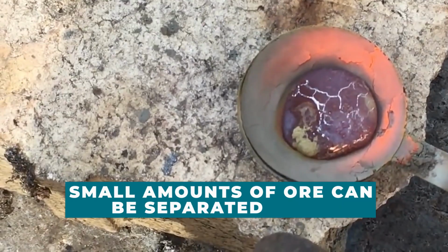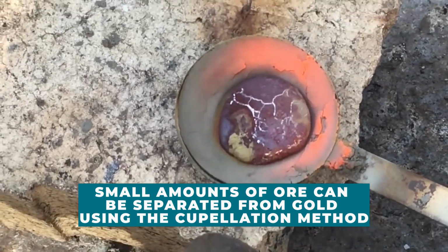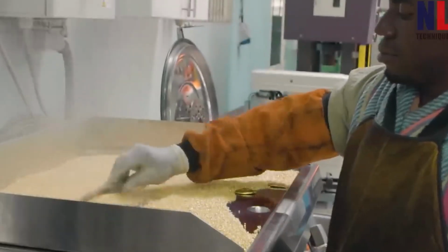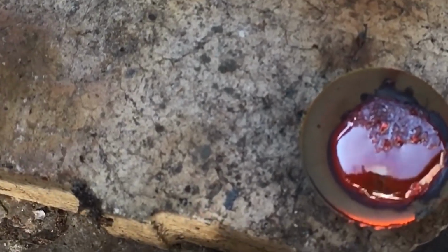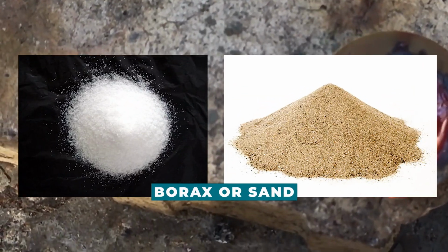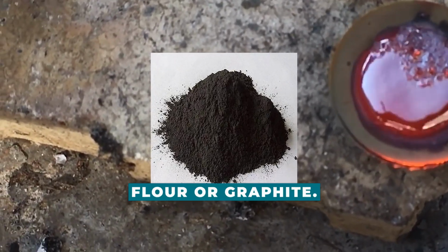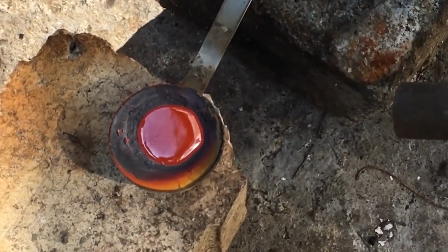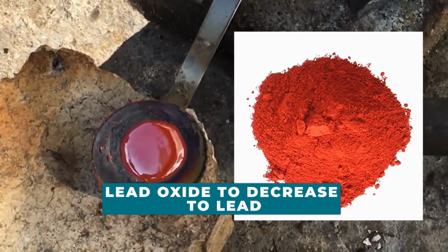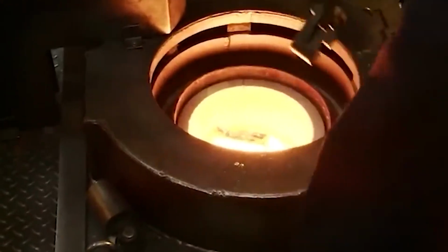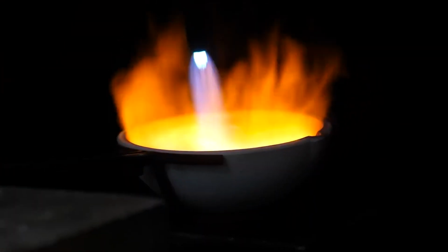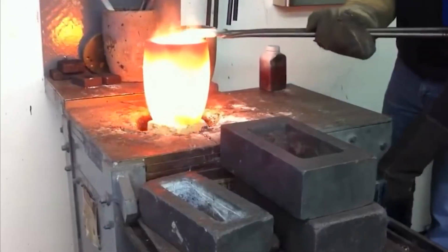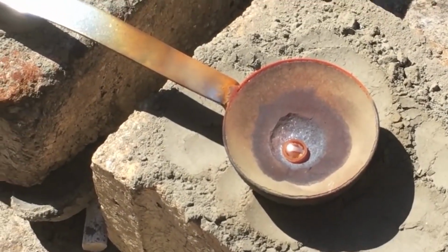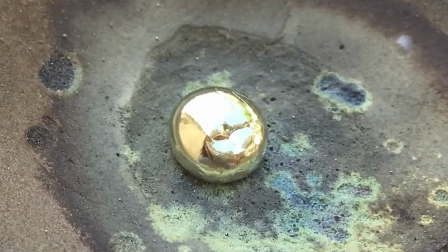Cupellation methods. Small amounts of gold can be separated from ore using the cupellation method. The ore is ground into a fine powder by the refiner, who then combines it with lead oxide, a flux consisting of borax or sand, and an organic reducing agent like flour or graphite. In a crucible, heating the mixture causes the lead oxide to reduce to lead, which then dissolves the gold to form a heavy molten phase. The phase is drained by the refiner and transferred into a second porous crucible from the bottom of the previous one. Lead, when heated, oxidizes, melts, and sinks into the walls of the crucible, releasing gold and other precious metals like silver and platinum.